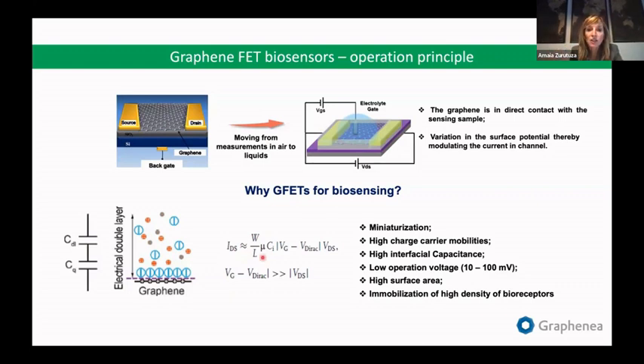The second point is the mobility. In the case of graphene, this mobility is very high. And another important parameter is the interfacial capacitance. This is also high in the case of graphene in comparison to, for example, silicon, as I will show you in a table on the next slide. And why is the interfacial capacitance of graphene high? Well, because we also have the quantum capacitance contributing to this interfacial capacitance, not only the capacitance of the double layer.